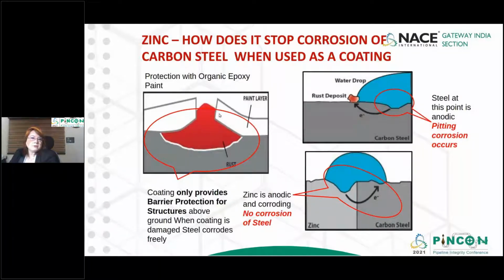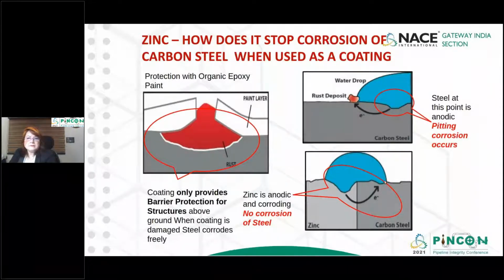With simple organic epoxy paints, the coating cracks, and corrosion starts, with rust formation here. Whereas when zinc is applied on carbon steel, zinc becomes anodic and there is no corrosion of steel. The electron moves towards the carbon steel in the affected area. This is pitting corrosion occurring with a normal epoxy coating.